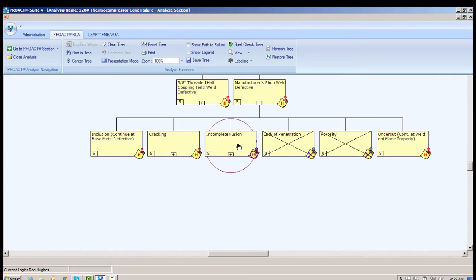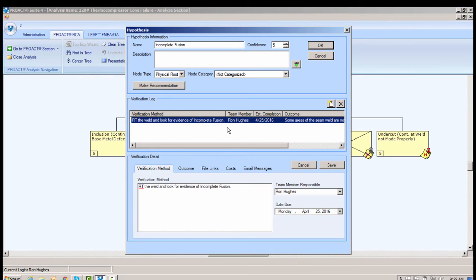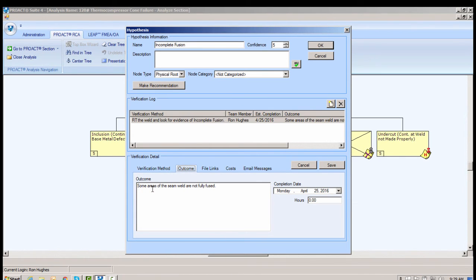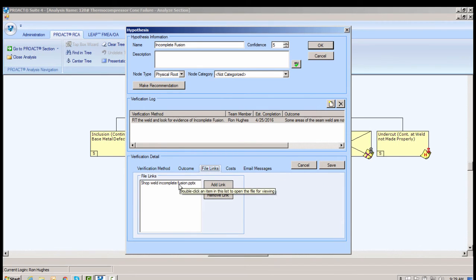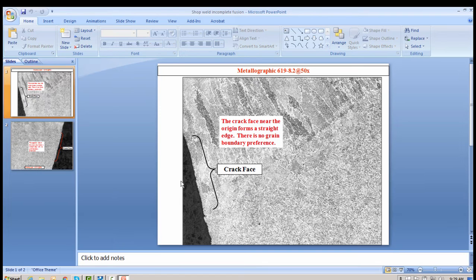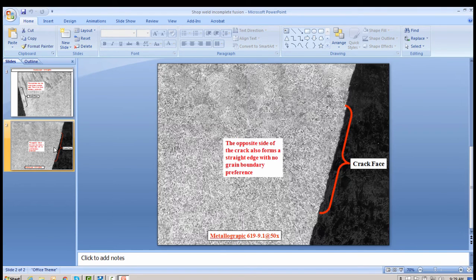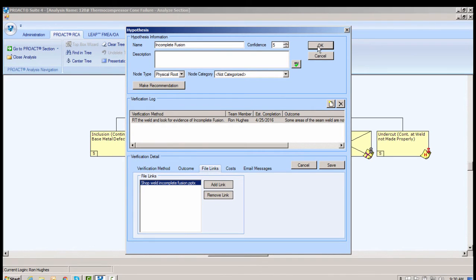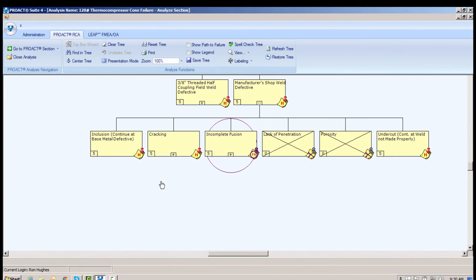But let's look at incomplete fusion here. We actually do have some incomplete fusion in this weld. So we RT the weld and we look for areas of incomplete fusion, and there are some areas that are not fully fused. And if we look at our x-ray, here we go, we can see the incomplete fusion here. There's no grain boundary here. That's what that is. And of course this is the other side of that particular weld. So there is some incomplete fusion in this weld. Let's check cracking again.